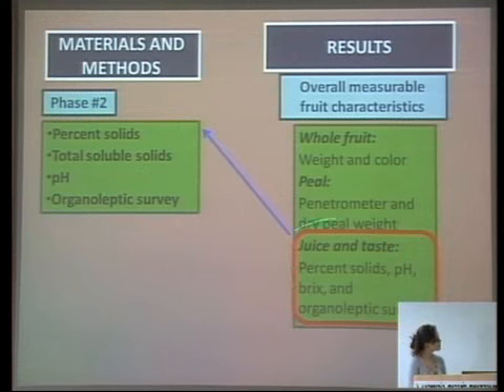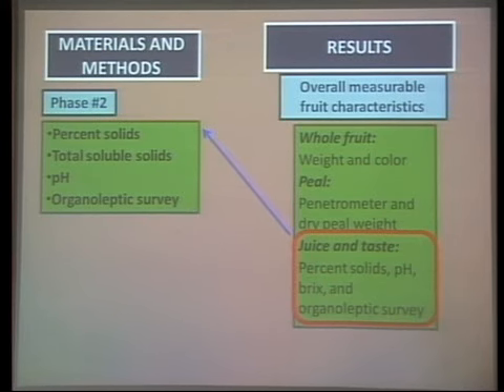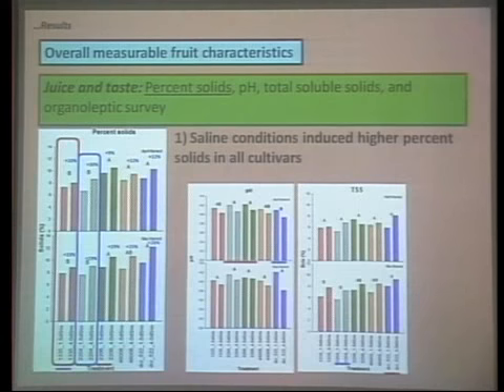Okay, the results that we acquired for percent solids, pH, TSS, and the organoleptic surveys were as follows. For all the cultivars, when they are grown under salinity, the percent solids increase. The cultivar that tends to be more susceptible, with percent solids increasing, is cultivar 1335, and the cultivar that is less susceptible is cultivar 2204. Nevertheless, the cultivar that has the highest percent solids, again, is the striped cultivar 2206, and the cultivar with the lowest percent solids is cultivar 1335.